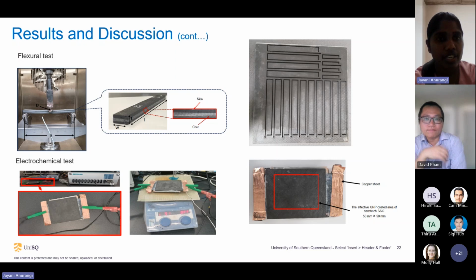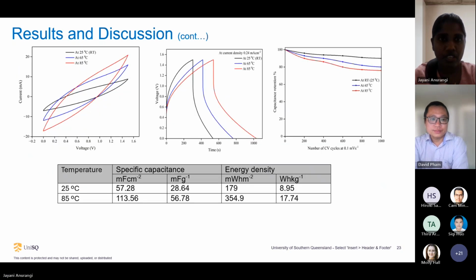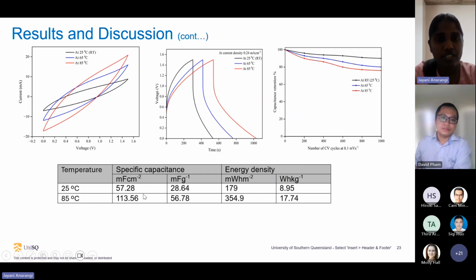When I do this test, I did it at 3 different temperature levels up to 85 Celsius. As shown in these figures, the first graph shows the CV test results. According to that, you can see that with the temperature, the energy storage has increased. According to this table, you can see the capacitance and energy density both have increased with the temperature, and it has doubled when the temperature is 85 Celsius.